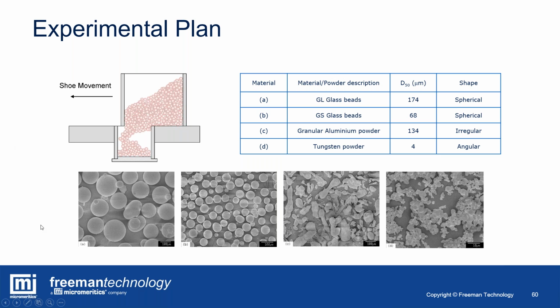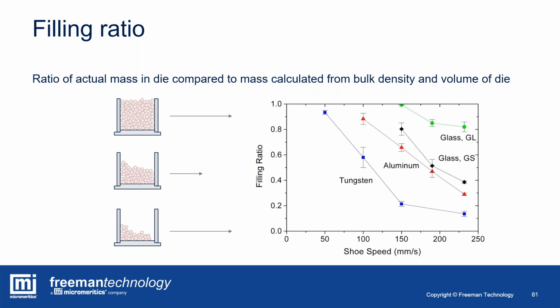We had a relatively large particle size granular aluminium powder, but an irregular morphology, as you can see in the image, and then a tungsten powder, which is a D50 of about 4 microns and angular in nature. And so we ran these 4 materials through the same setup with different shoe speeds, and we assessed what we call the filling ratio. So the amount of material that actually transferred from the shoe to the die on that single pass as a function of shoe speed.